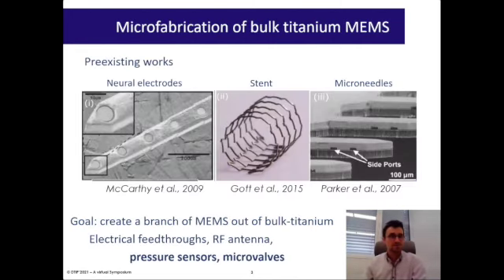In the past years, recent developments have been made to try to overcome these limitations of resolution. The strategy used was to transpose some microfabrication techniques from the silicon industry and to apply them to titanium. One of the biggest milestones achieved was the development of deep reactive ion etching techniques for titanium, as Rina Curie introduced yesterday morning in her presentation.